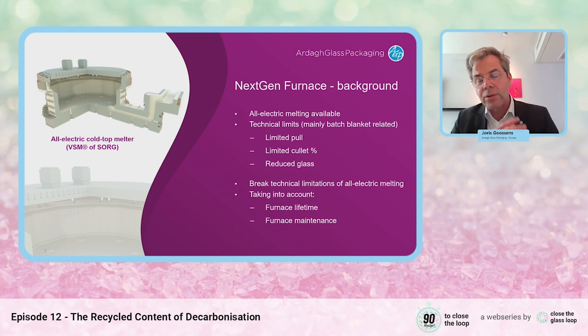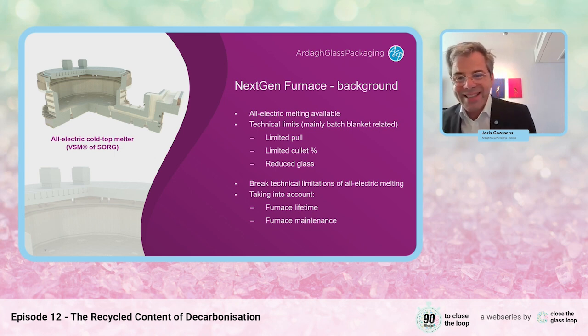And the idea is now to see, can we break these technical limits and remain as all electric as possible, taking into account that using all electrical heating at a high level affects the furnace lifetime. Because of the higher glass temperature and the more intense glass flow, the furnace lifetimes are shorter, and also the way they wear and the way you maintain the furnace are different.